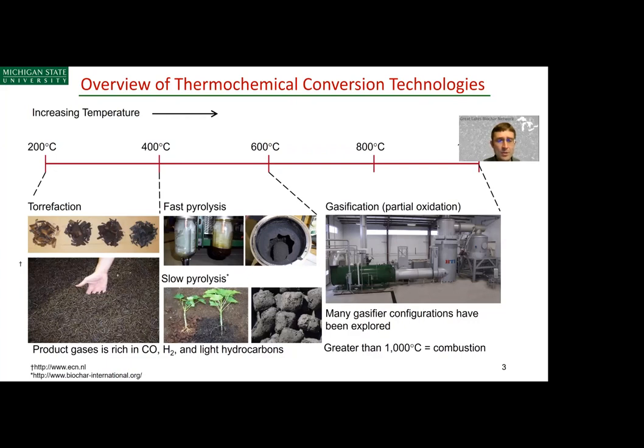As we move up this temperature range into the 400 to 600 degrees C range, this is where the technologies of pyrolysis are employed. They can be employed as either fast pyrolysis, which rapidly heats biomass in the absence of oxygen, or slow pyrolysis, which much more slowly heats biomass in the absence of oxygen for much longer residence times. Fast pyrolysis residence times are on the order of seconds or less. Slow pyrolysis residence times can be minutes to hours to days.